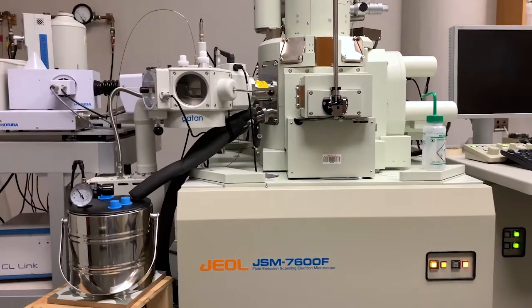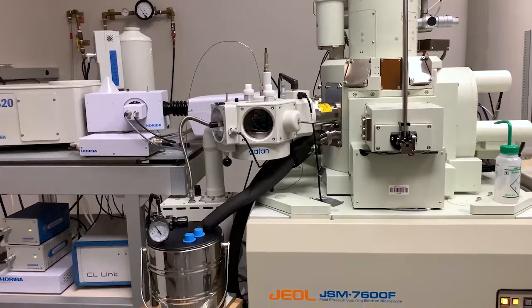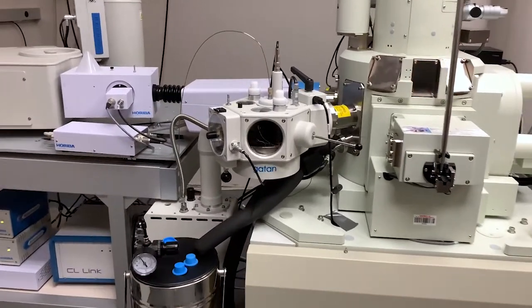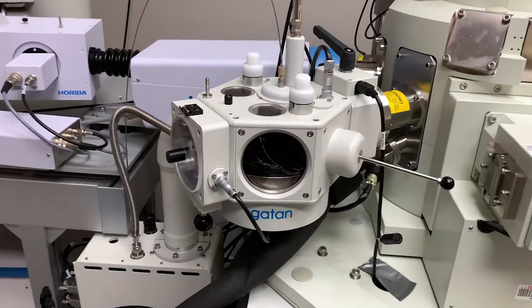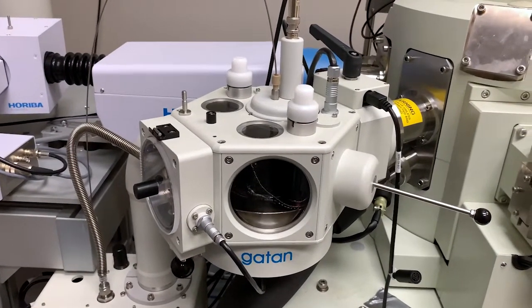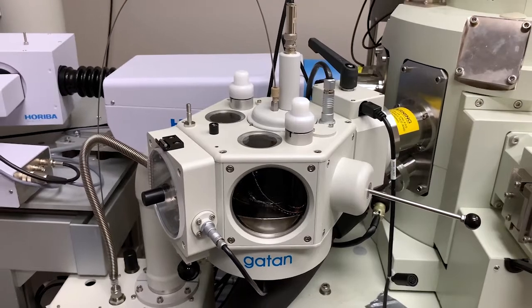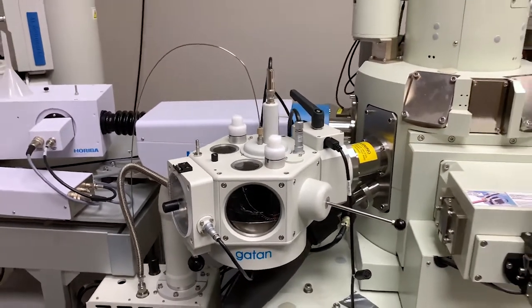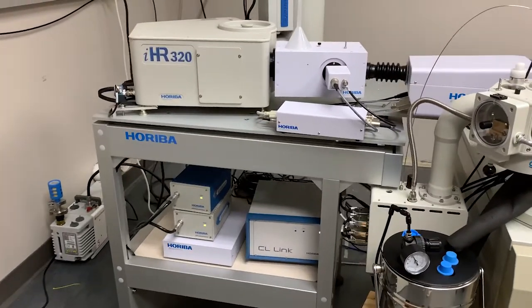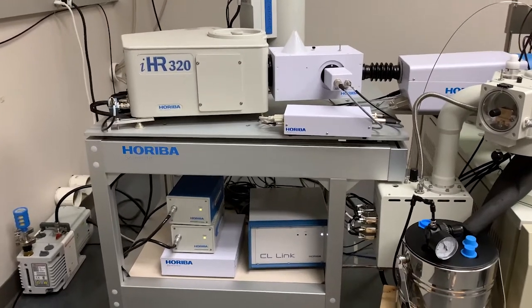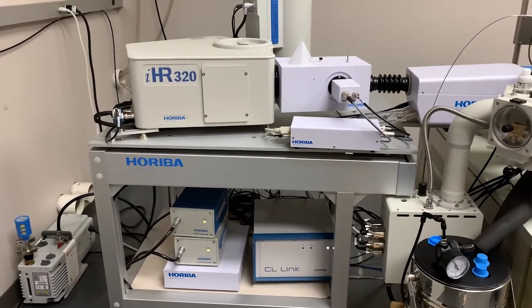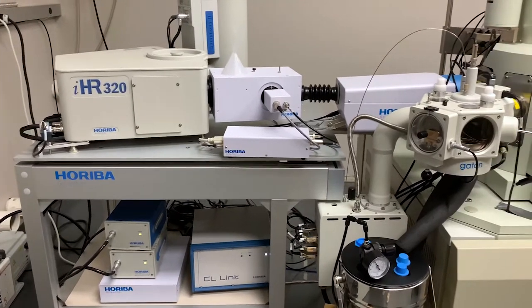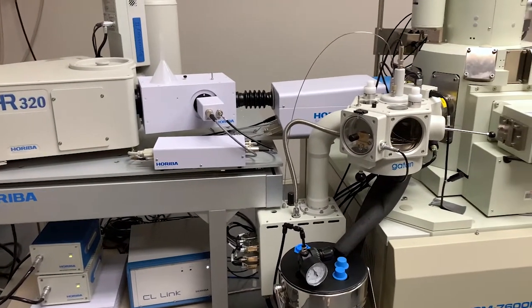The JEOL JSM-7600F SEM outfitted with a cryogenic transfer system, in situ gold platinum sputter coater, and cold stage, and this can be used to evaluate hydrated samples without the need for drying, making it an ideal imaging tool for volatile or beam-sensitive samples. This SEM is also equipped with a complete cathodoluminescence solution to analyze CL signals over a wide spectral range from 200 nanometers to 2200 nanometers.